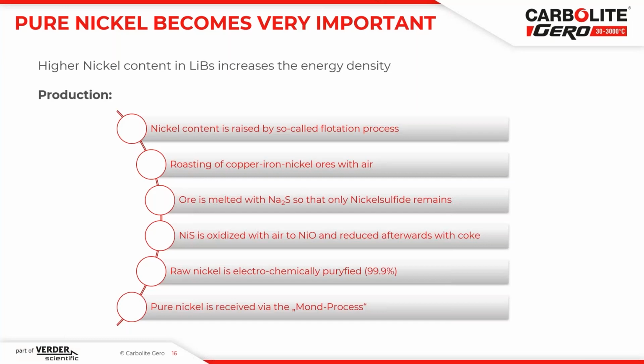In the next step, the iron, copper, nickel ores are roasted with air. Then the ore is melted together with sodium sulfide, and only nickel sulfide remains. This is due to the fact that the copper forms a soluble liquid phase, and this is then easily physically separated from the nickel sulfide. The nickel sulfide oxidizes later on with air to nickel oxide, and it will be reduced afterwards with coke. The raw nickel is then electrochemically purified, or, to get a higher purity of the nickel, the Mond process is used on a high scale.